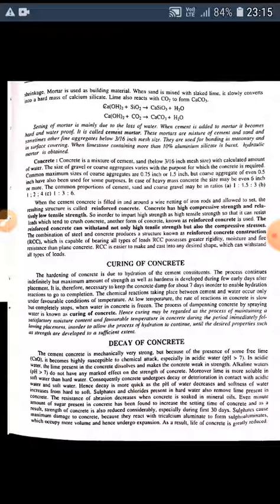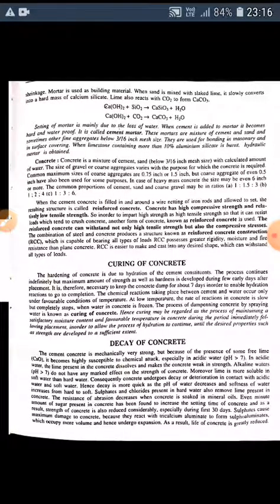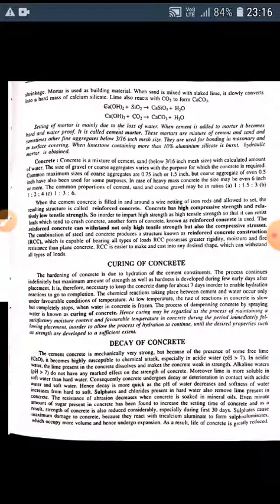The hardening of concrete is due to hydration of the cement constituents. The process continues indefinitely, but maximum amount of strength as well as hardness is developed during the few early days after placement. Therefore, it is necessary to keep the concrete damp for about 7 days in order to enable hydration reactions to go to completion. The chemical reactions taking place between